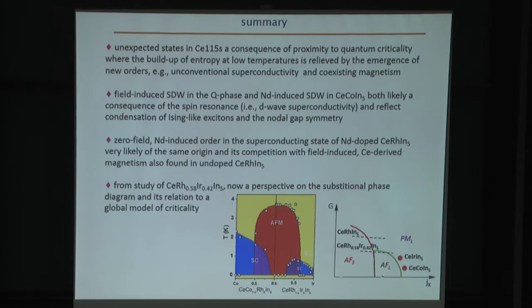So let me just summarize then by saying that we found now evidence for unexpected magnetic states that develop inside the superconducting phase of these cerium 115 materials. These unexpected states are, in my opinion, a direct consequence of the proximity of all these cerium-115s to quantum criticality, where the buildup of entropy at low temperatures can be relieved then by the formation of orders such as unconventional superconductivity and coexisting magnetism.